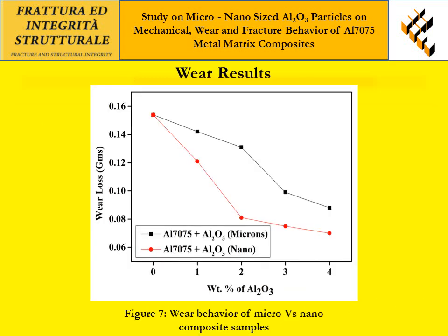Figure 7 shows the wear rate of micro versus nano composites. It is concluded that adding hard ceramic particulates like Al2O3 into the aluminium considerably enhances the wear resistance of MMCs. The wear rate of nanocomposites shows improved wear resistance when compared to the microcomposites.